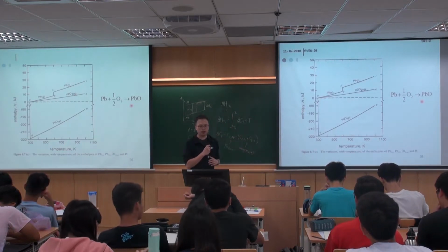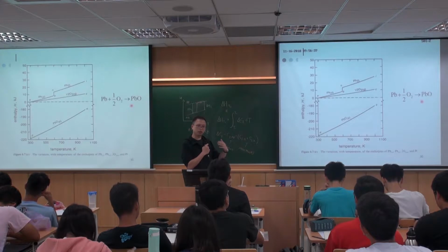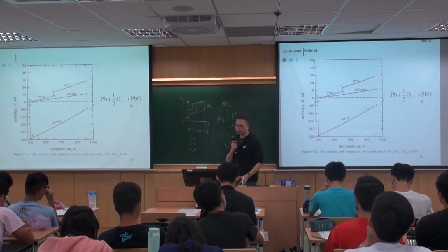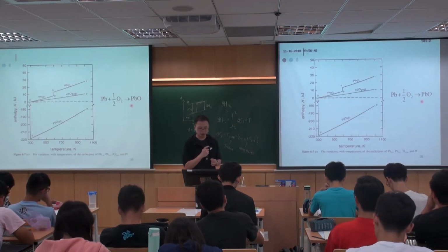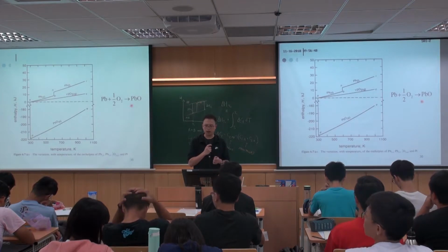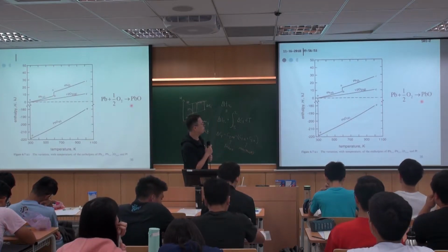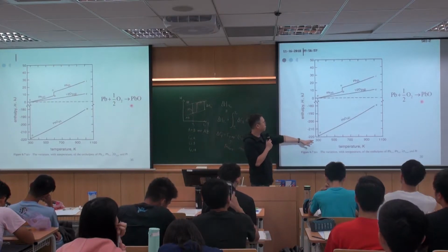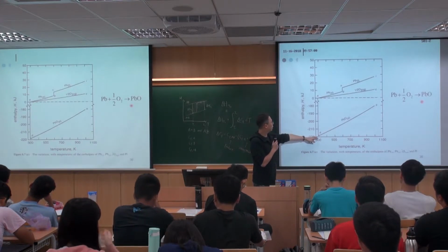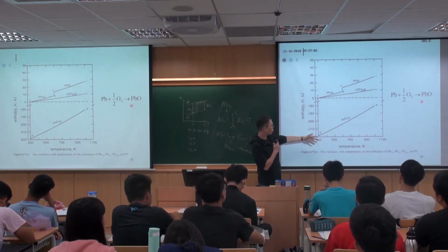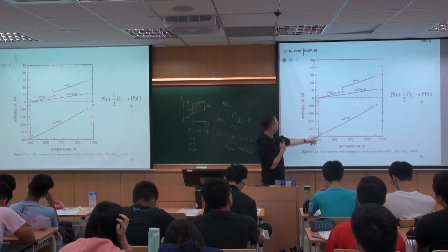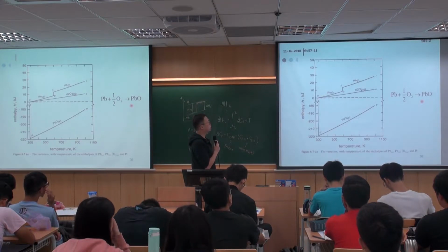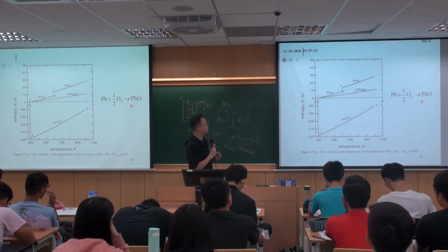So even when it is heated up to 700 Kelvin, it is still solid. Okay, it is still solid. So it's a pretty straight line, and there's no jump, which means that there's no phase transformation. There's no melting of lead oxide up to, say, 1,000 Kelvin. And if you look at the intercept, for lead oxide, the intercept to 298 Kelvin, or around 300 Kelvin, is this value. It's about minus, say, 220 kilojoules. So that's the formation heat of lead oxide.